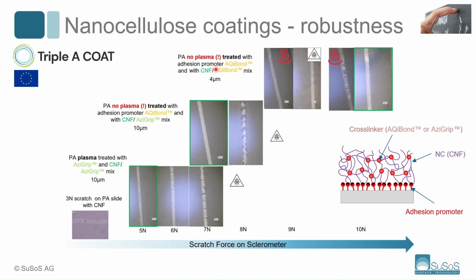If we use both for cross-linker and for adhesion promoter the AQiBond with the azide low temperature activation group, upon UV curing or temperature curing, we achieve 9 to 10 Newtons, which is very good. It's a very robust coating and can be easily used as a coating in the bus. So the non-plasma protocol and the new class of adhesion promoter and cross-linker AQiBond with the low temperature activation works very well.